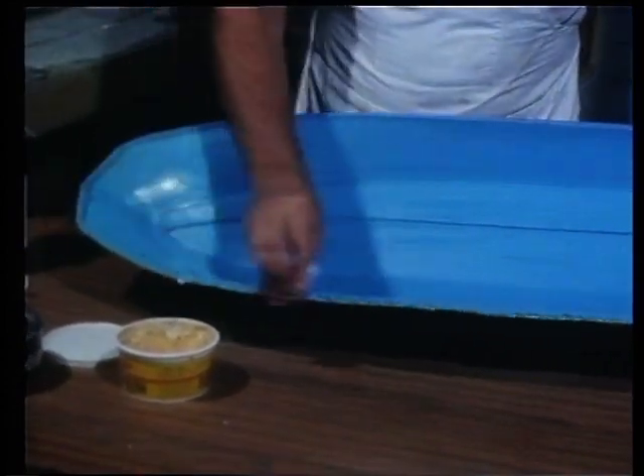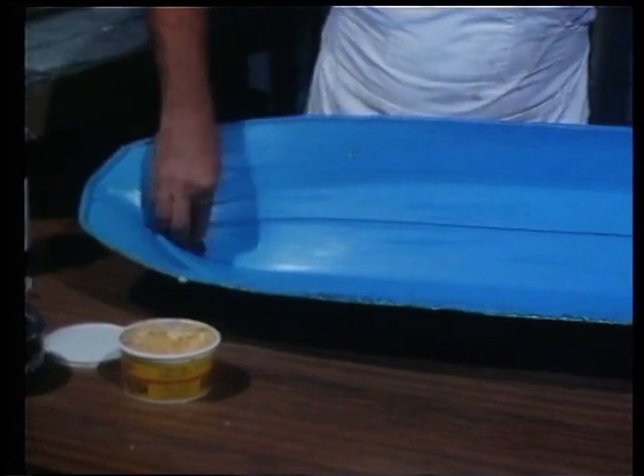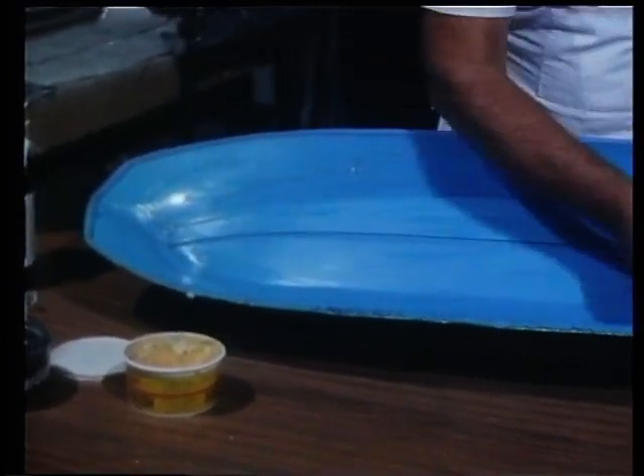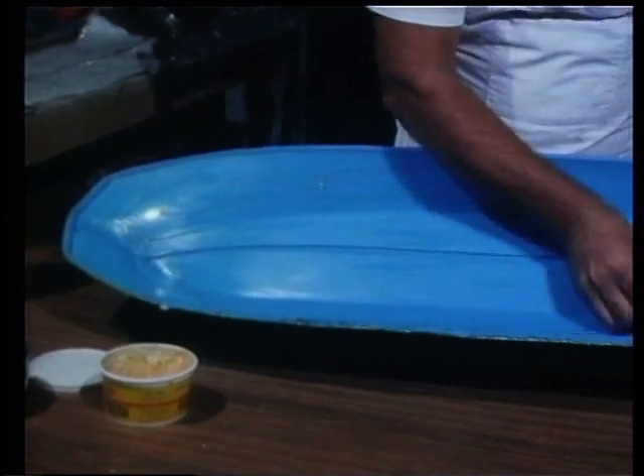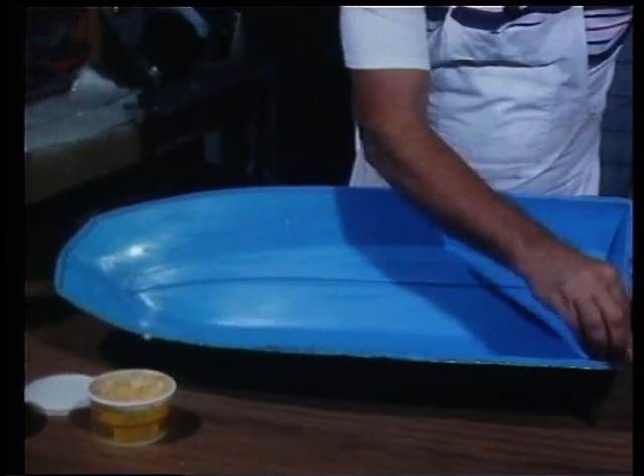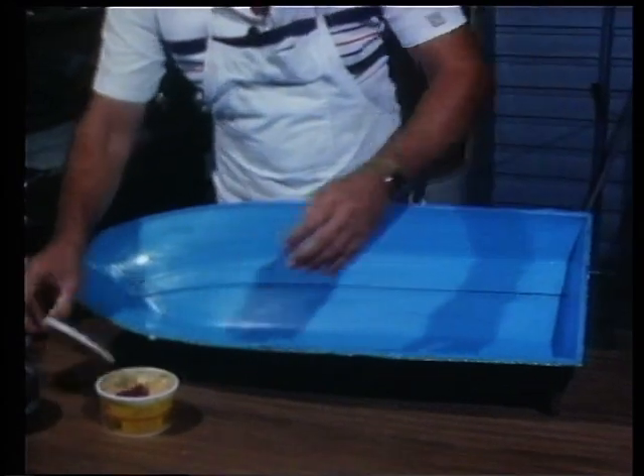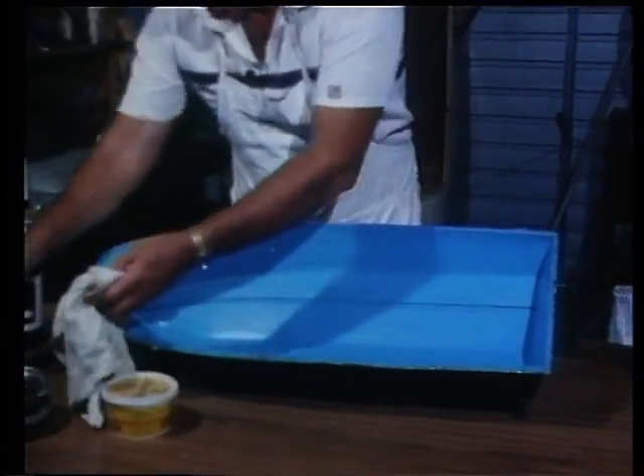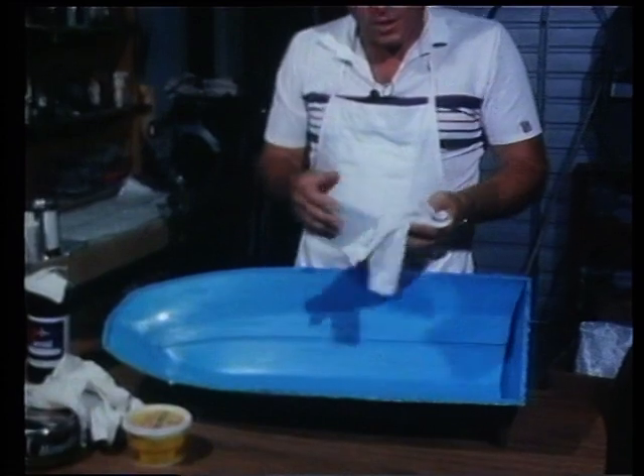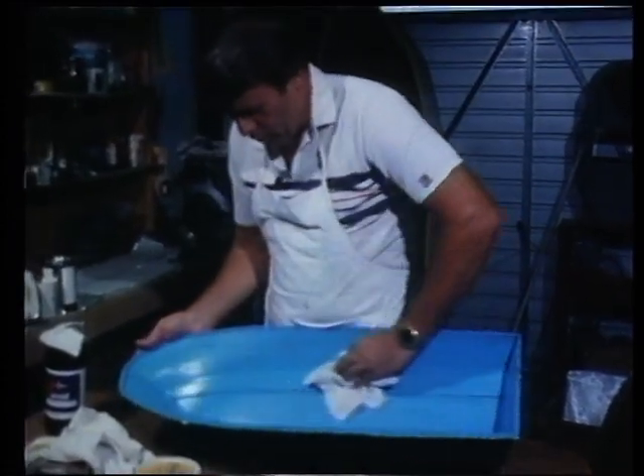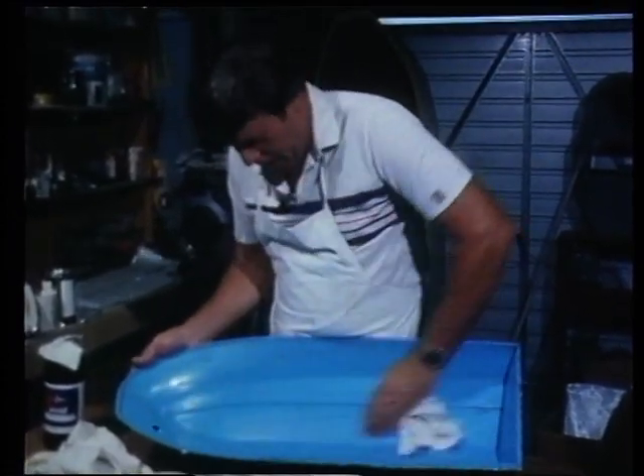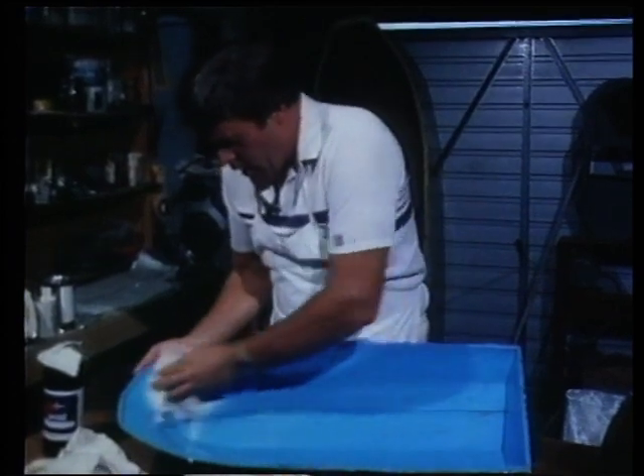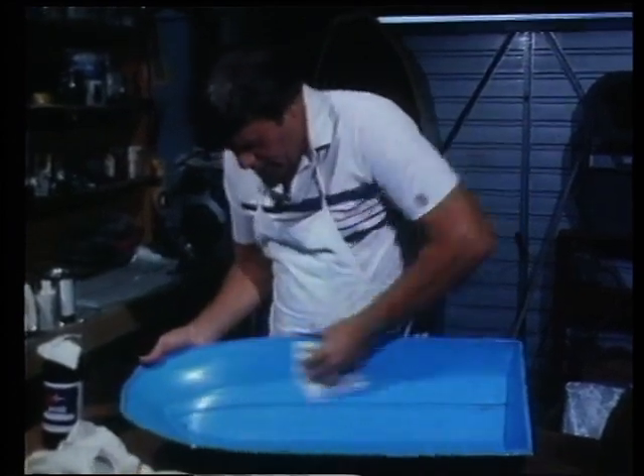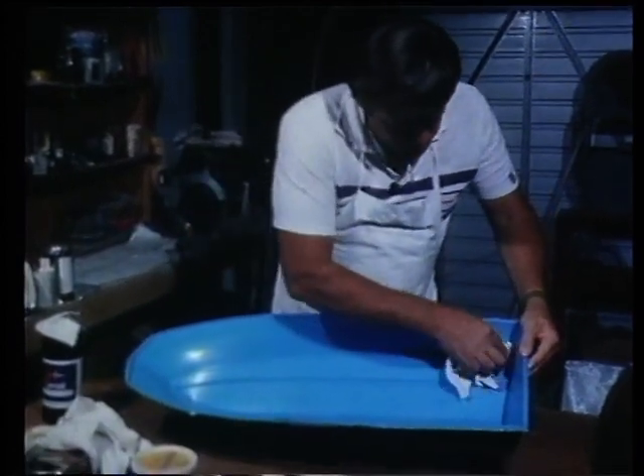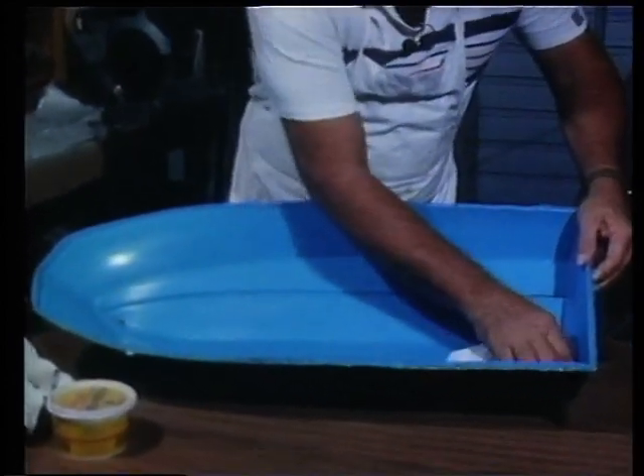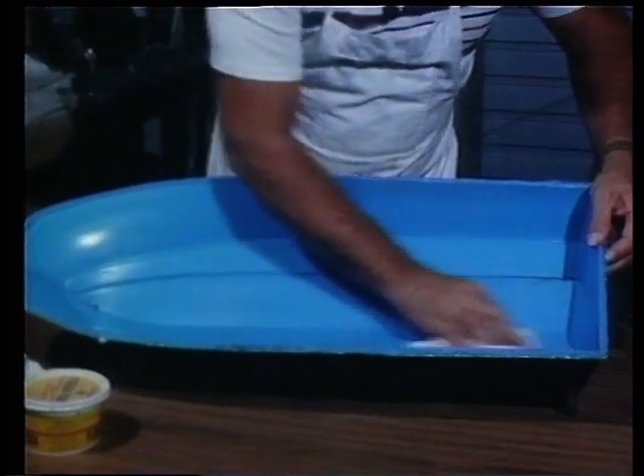As with any application of fiberglass, as with any stage during the building of a fiberglass boat, absolute thoroughness is essential, and if you exercise that, in fact if you're overcautious, you'll find that you won't have any problems whatsoever. Now immediately the wax goes in, and most importantly before it dries, you polish it straight back out again. The wax is not necessarily designed to impregnate the surface, it's only really there to alter the surface tension of the mould to prepare it for the application of the liquid release agent.